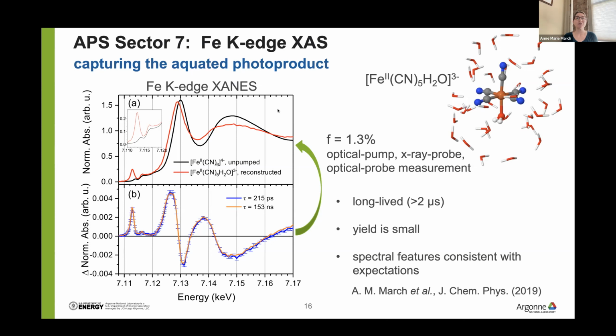Then we did something a little bit crazy: while doing this measurement, we also incorporated an optical probe in order to measure the amount of aquated product we were producing. By doing this, we could determine the excitation fraction precisely. We found we were producing 1.3%, and with this, we could reconstruct the absorption spectrum for the aquated product. That's what you see in red. So this was pretty cool.